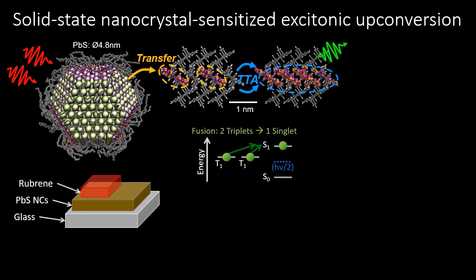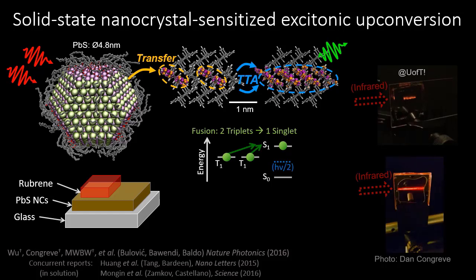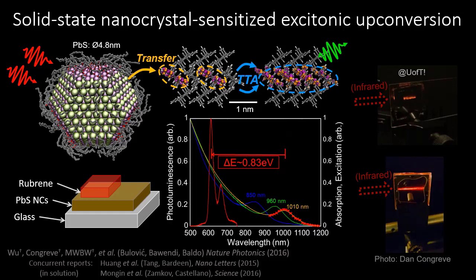The general scheme is to set up something sensitized by a semiconducting nanocrystal that absorbs red light, spin-mixes rapidly, and transfers that energy to sensitize the spin triplet state in an organic molecule. The triplet organic then diffuses spatially or energetically through a film, comes together, and makes green light. This is something I demonstrated at the end of my postdoc at MIT working with Dan Congreve, Mengfei Wu, and the groups of Moungi Bawendi, Vladimir Bulovic, and Marc Baldo. We showed that this worked quite well — upconverting from beyond 1000 nanometers, observing red emission at 612 nm while exciting with a laser at nearly 1.1 microns, doing this in solid state with a film of rubrene on top of a film of lead sulfide nanocrystals.